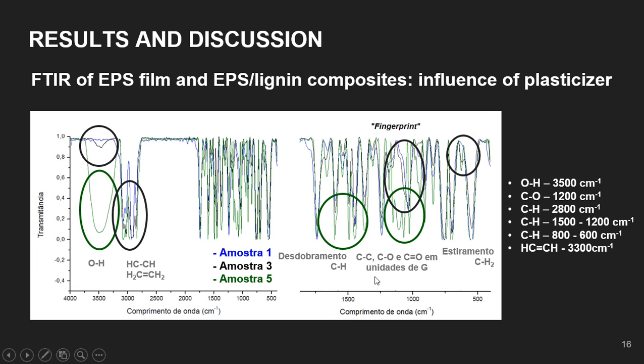carbon-oxygen, and carbonyl linkages of guaiacyl groups of lignin, in addition to a slight displacement of approximately 610 cm that can also occur due to the presence of alcoholic groups constituents of lignin. This band shows that there was an interaction between the matrix and the reinforcing agent.